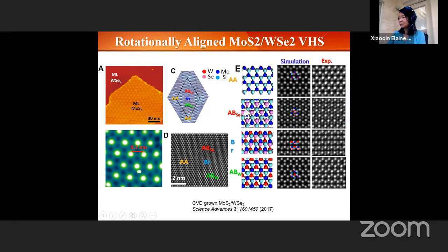But when I move tens of a unit cell away, I can see one of the chalcogenide atoms now stick out, the bottom layer sticking out in the center of the top hexagon. And then I have another situation where it's reversed. I have three high symmetry points, and at these three symmetry points the atomic alignment is such that I still have the threefold rotational symmetry. So they're a little special in optical properties.